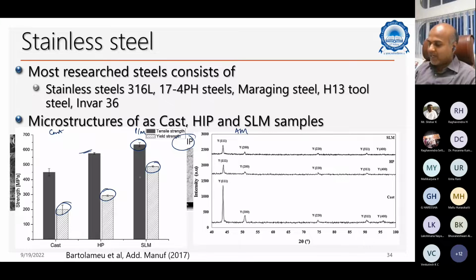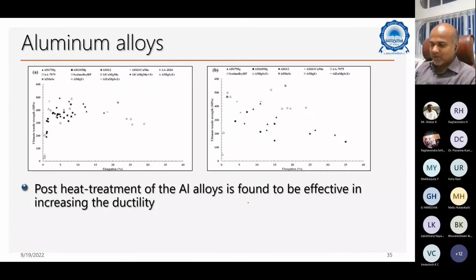If we look at the XRD pattern of these three materials, this is SLM, HIP, and as-cast, you see that as-cast has more intense 111 peaks compared to the other two, which shows that there is a certain kind of preferred orientation, or texture, in this material. Now let's talk about aluminum alloys.